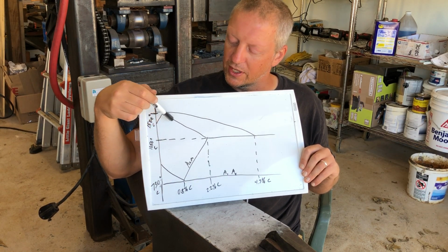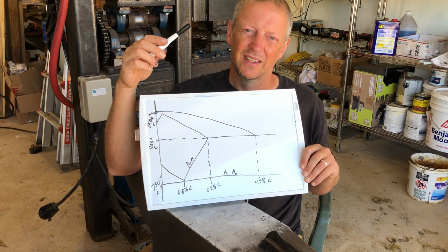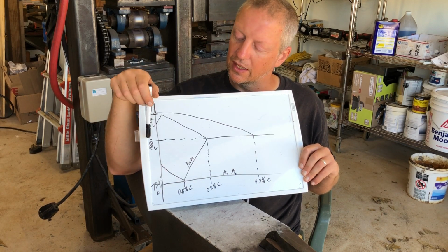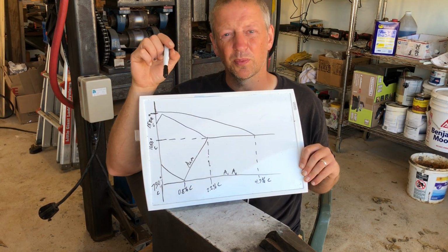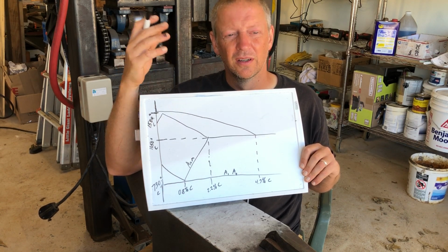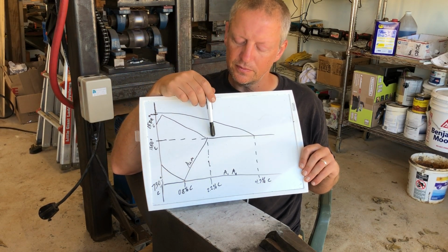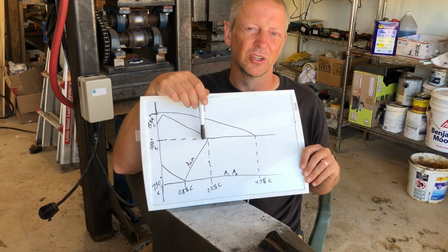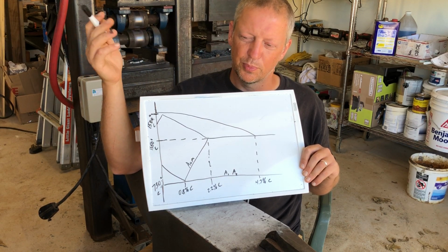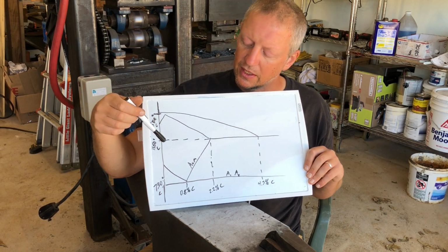So basically, if you trust this line implicitly, you might get into some fishy territory. The 1150 C, that's essentially guaranteed unless you have some other impurities in there that affect this temperature, affect your hot short temperature. Prime among those would be sulfur, but again, we'll get into that in another conversation.